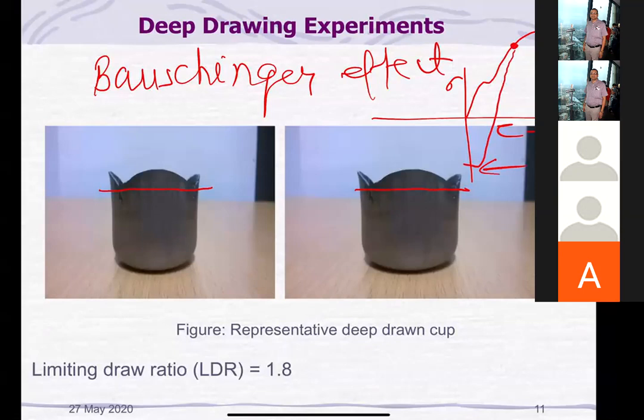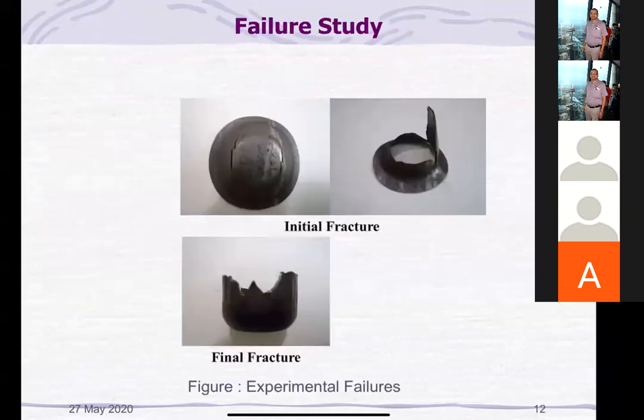There is a whole science behind it, dislocation theory, and I'm not going to get into it. So this phenomenon is very strong in titanium below 400 degrees centigrade. So due to that, what happens? See, the fracture appears in this region. Of course, there will be a fracture at the punch corner radius. This is the initiation of fracture, and this is the final fracture. But due to the strong Bauschinger effect, the fracture also appears in the wall.